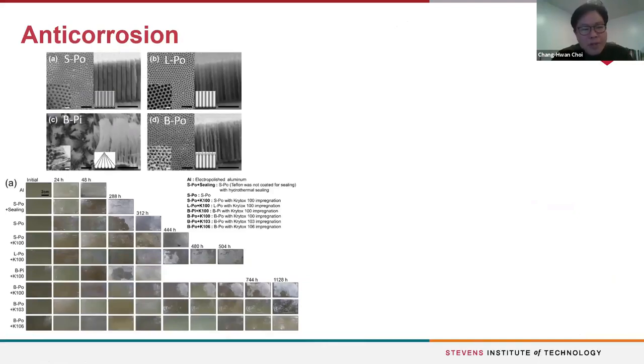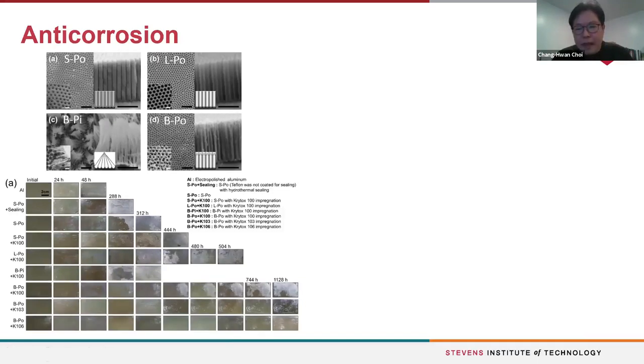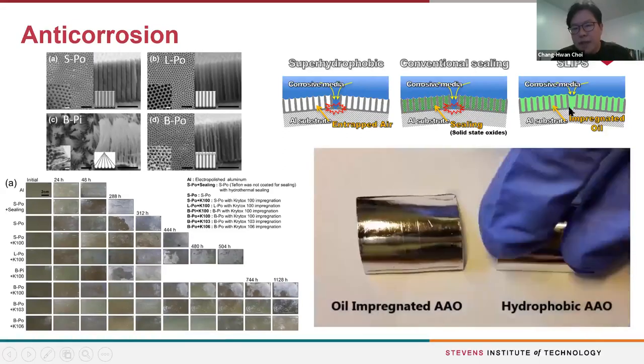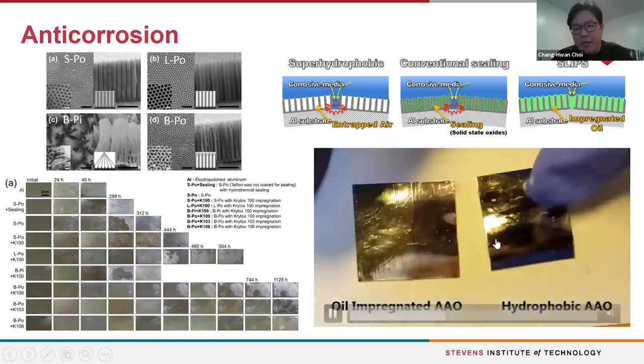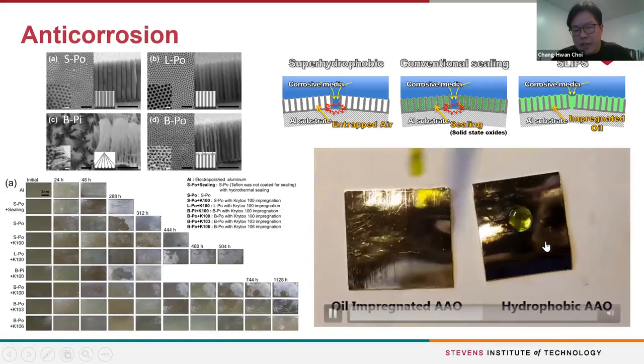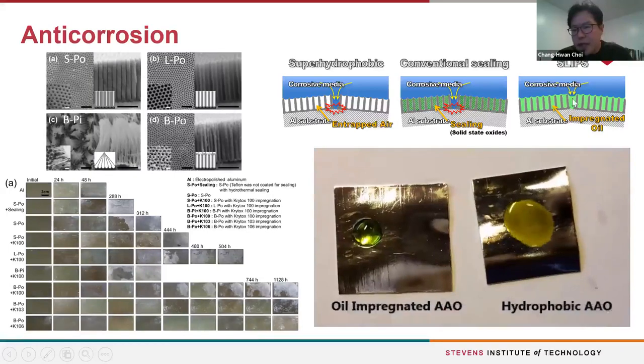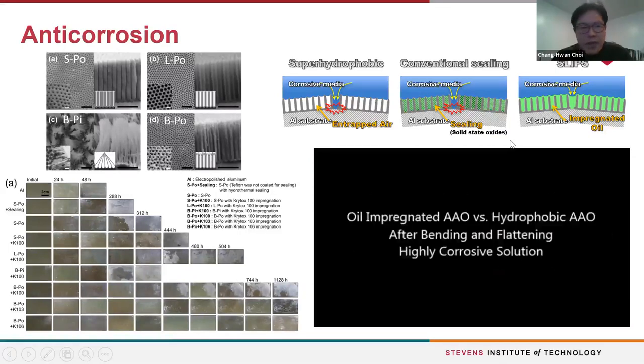We can also use this for corrosion protection. Since our surface is protected by an air layer or a liquid oil layer, we can prevent corrosion of the substrate. We tested our surfaces in harsh salt fog environments for several weeks and observed no significant corrosion. Comparing super-hydrophobic surfaces to SLIPS, the SLIPS surface shows self-healing capability: if cracks are made intentionally and a highly acidic liquid is applied, the liquid oil layer flows to fill the damaged area, maintaining anti-corrosion effects.